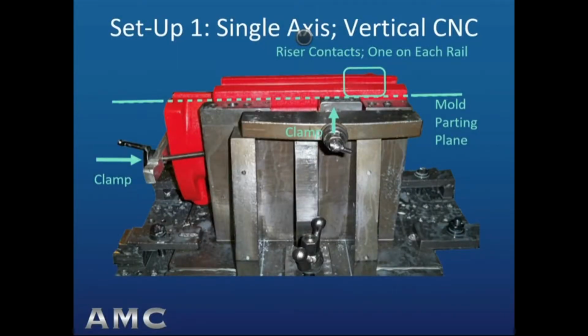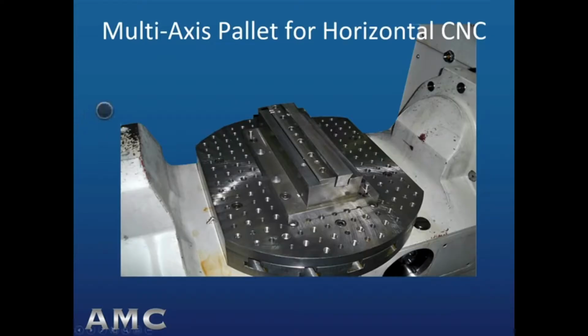Here, there is no draft issue, and the clamping and targeting is a simple across the width of the casting and along its length. As noted previously, the riser contacts are machined away in the face milling of the dovetail features. Here is the pallet for a horizontal machine tool that rotates in two planes. Mounted on the pallet is the fixture that will clamp onto the dovetails machined in the first fixture.